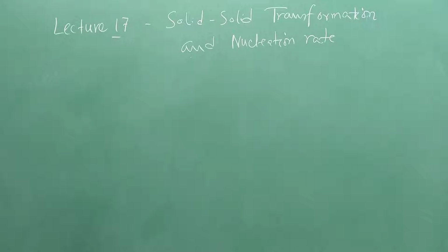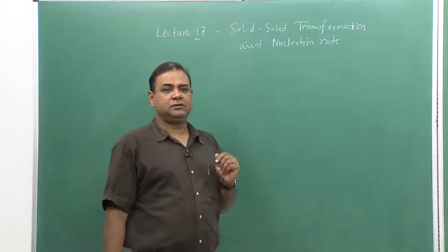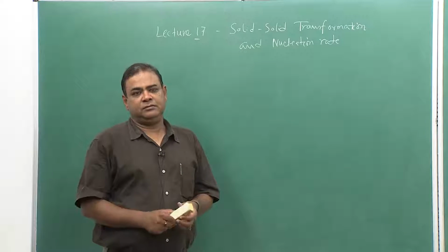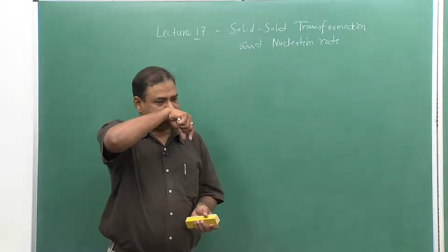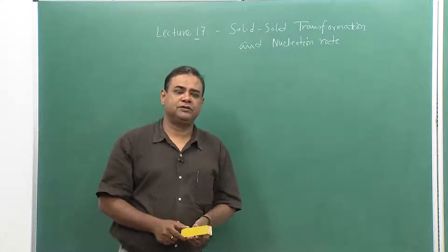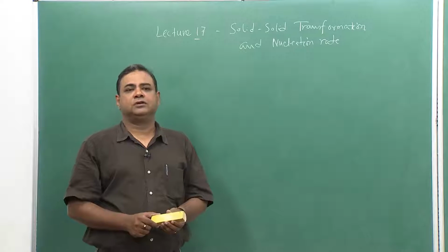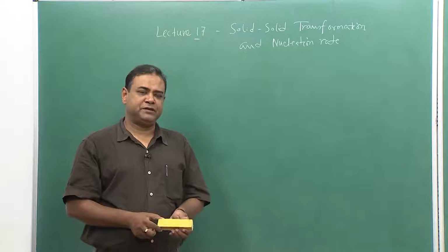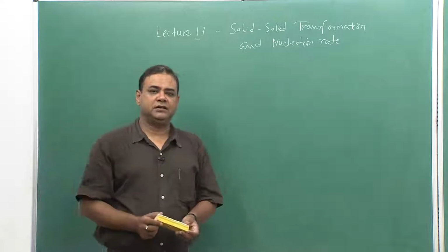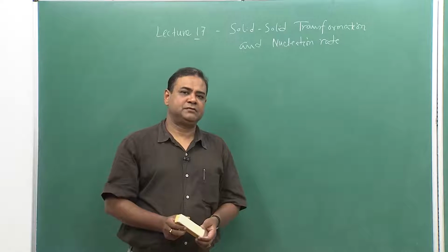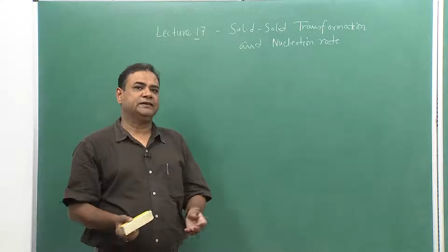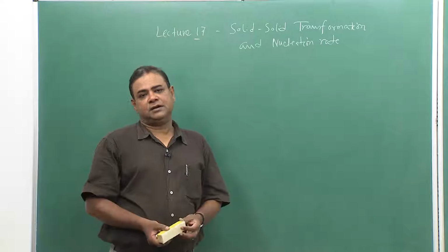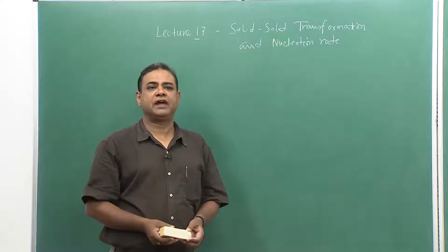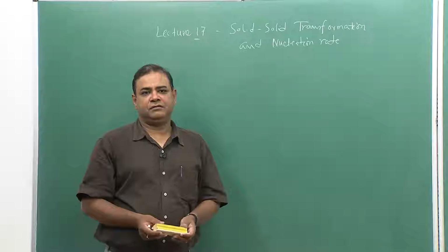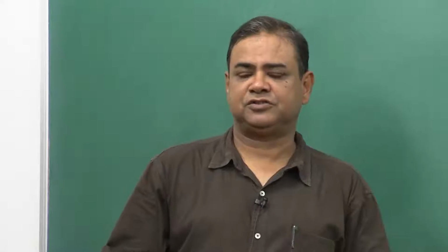So, whenever we talk about solid-solid transformation and nucleation rate, because this is extremely important, we started with liquid-solid transformation, but most of our heat treatment will be associated with solid-solid transformation. Of course, solid-liquid transformation also warrants a lot of heat treatment procedures. For example, during casting, we have to look at different temperature and time considerations in order to get the desired structure and finally desired properties. But in case of steel, we always come across heat treatment like annealing, normalizing, and martensite formation, which is called hardening. So, those will be in solid-solid transformation situations.